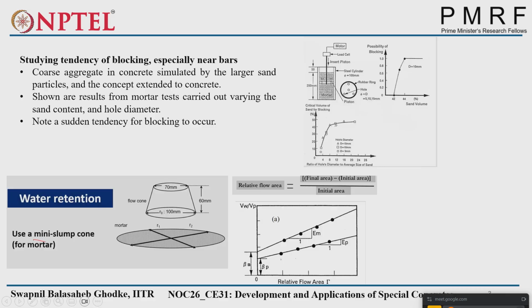Here it is zero flow, right? Means concrete is more stiff. Here, as we are increasing, flow area is increasing, because you can see the volume of water to the volume of powder ratio increases. Ultimately either powder content decreases or water content increases. If water content increases, obviously flow will increase. That's why flow area also goes on increasing. So what is the zero flow area indicating? Can anyone guess? Based on visual interpretation, what can you say about beta M, which is related to the mortar, and beta P, which is related to the paste, at zero flow?